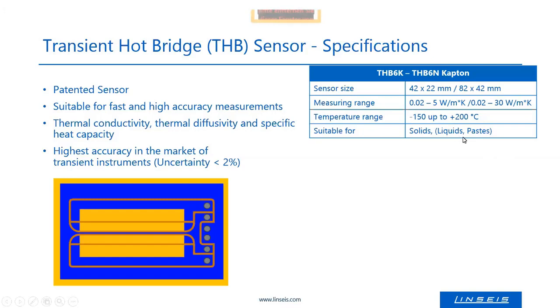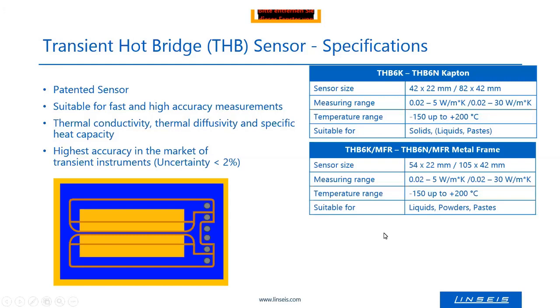But for liquids and pastes, only the pure sensors without a metal frame around them can be used, if the viscosity is not too high. If you have liquids, powders, or pastes, or liquids with a higher viscosity, a metal frame needs to be placed around the sensor to stabilize it. And then the specifications are the same.